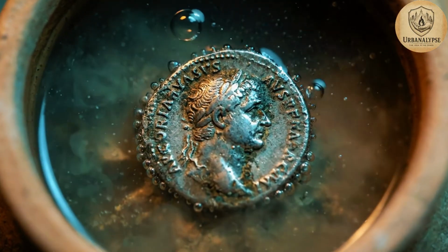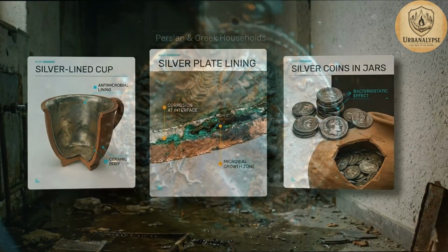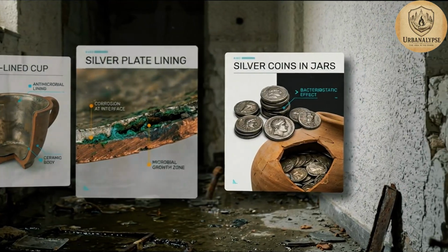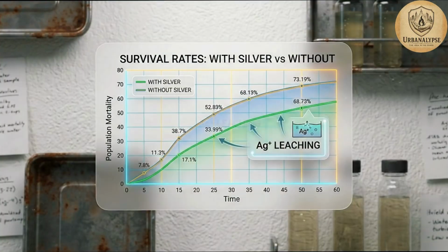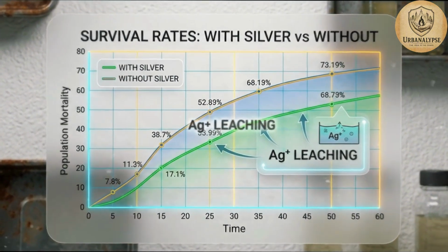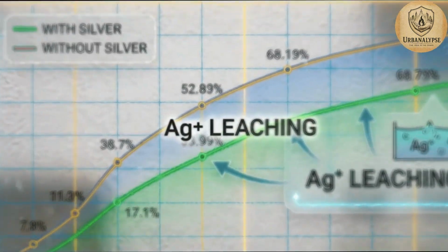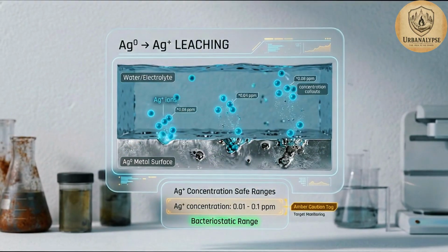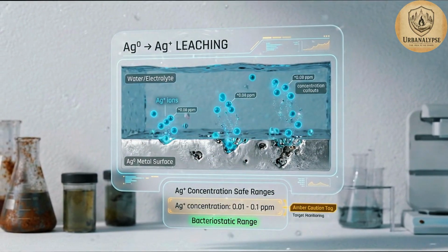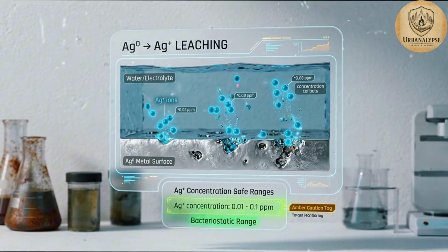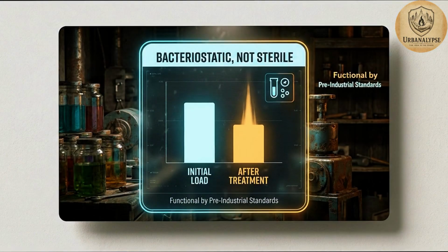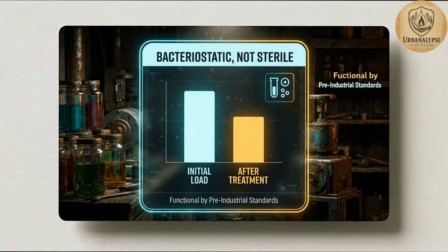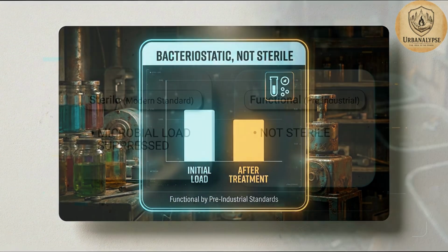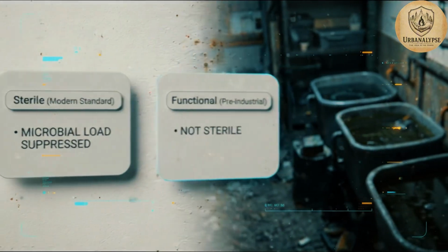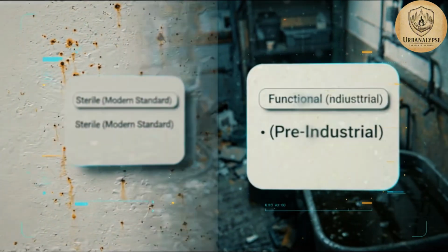It's in recorded history. Silver coins placed in water storage vessels, silver plates lining containers, silver-lined drinking cups in Persian and Greek households. These were empirical experiments conducted over centuries, validated by differential survival outcomes between populations that used them and populations that didn't. The mechanism: slow Ag+ leaching from the metal surface at concentrations low enough to avoid acute toxicity and high enough to maintain bacteriostatic conditions. Microbial load suppressed, not sterile by modern standards, functional by any pre-industrial survival standard.